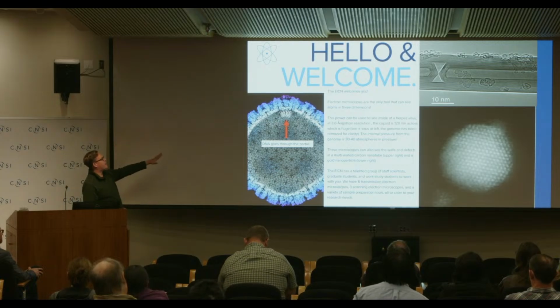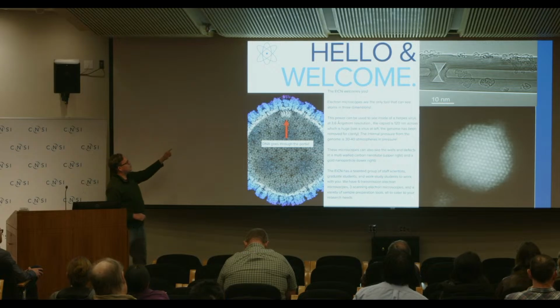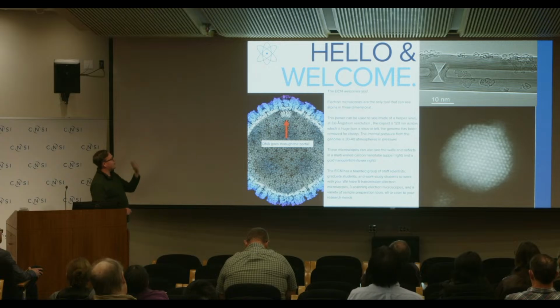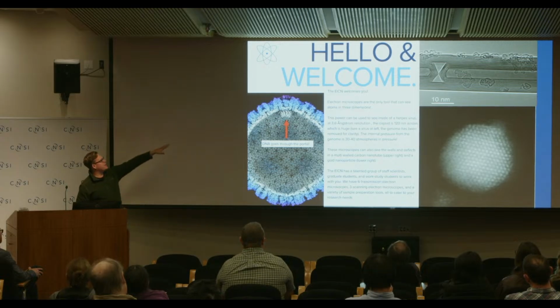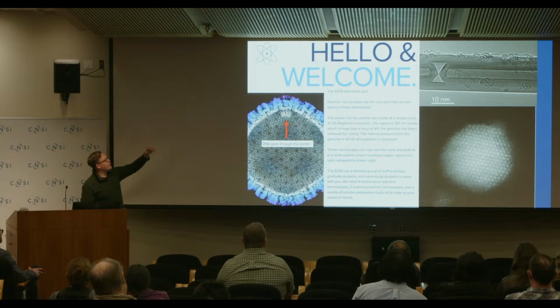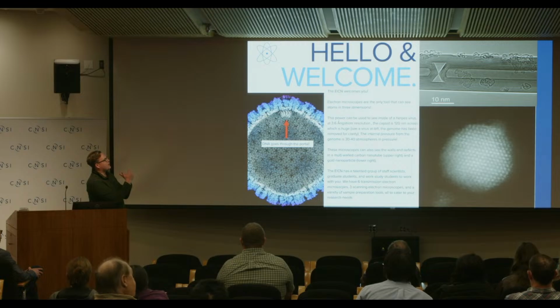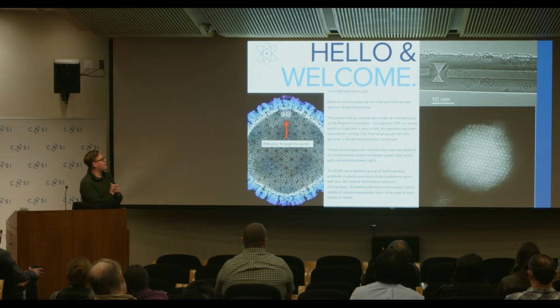Here's another example of a virus. This is a little capsid that's absolutely enormous. This capsid's about 120 nanometers across, and you can actually see cool details like this little portal where all the DNA comes in and out of the capsid here. You can use these electron microscopes to see the individual walls of a carbon nanotube. So that's what we have at the upper right. And those walls are about 3.4 angstroms in size. And even though this carbon is very, very sensitive to the beam, we can actually image at that level. Here's another example of a gold nanoparticle imaged at atomic scale.